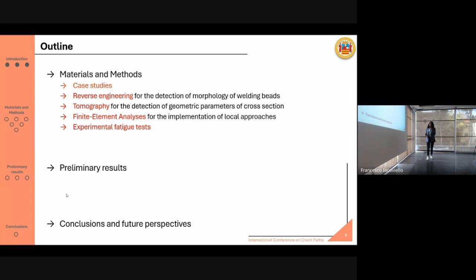Then we carried out some computed tomographies for the detection of the geometrical parameters of the cross-section of the specimen in order to construct a numerical model and carry out a finite element analysis for the implementation of the local approaches. And finally, we carried out some experimental fatigue tests.